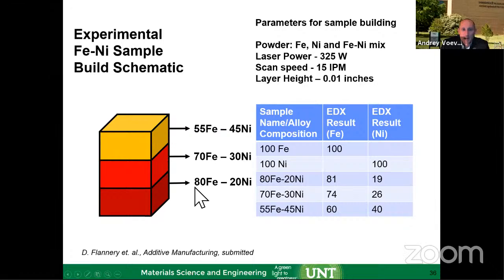And first we have iron rich and less nickel, then we add more nickel and less iron, and then we finish with even more nickel, 45% nickel and 55% iron. So it's kind of a model system in the iron-nickel system where we know what powder we're feeding in the nozzles, and therefore we can correlate to the spectral signal from iron and nickel characteristic peaks.